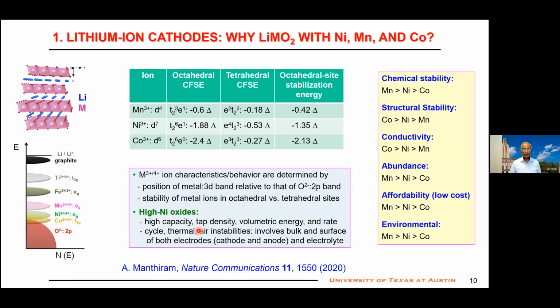The next factor is structural stability. These ions are in the octahedral sites in the crystal lattice. So one can calculate the crystal field stabilization energy in the octahedral site and in the tetrahedral site. If we take the difference, that will tell us to what extent these ions love the octahedral site and hate the tetrahedral site. In the case of cobalt 3+, all the 6 electrons are in the low-lying t2g band. Therefore, it has high stabilization for octahedral site. That means cobalt loves octahedral site, it hates tetrahedral site. Manganese, on the other hand, has a small difference, it can easily migrate from the octahedral site through a neighboring tetrahedral site to this lithium plane. So if it does, 25% migration from here to here will transform the material from layered structure to spinel structure, and the voltage will decrease.